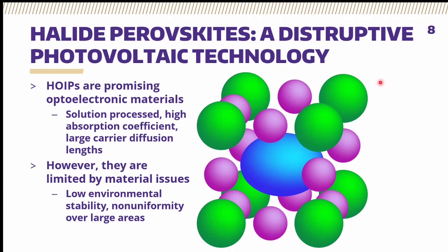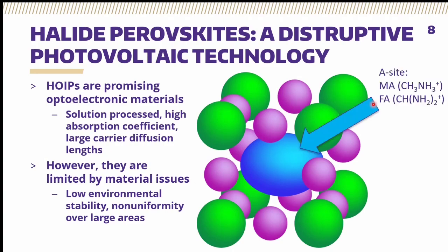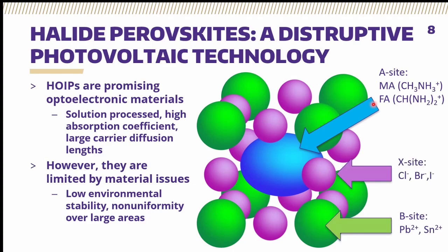The perovskites themselves have this structure here, this cubic crystal structure with an organic A site, usually methyl ammonium, abbreviated MA, or formamidinium, a B site that consists primarily of lead with sometimes tin, and a halogen X site, usually iodide, but sometimes bromine, and even a little bit of chlorine from time to time.